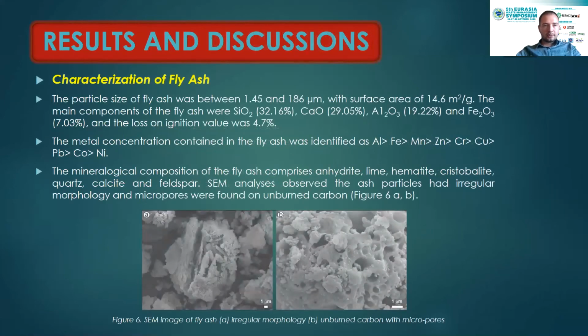Results and discussions. Characterization of fly ash. The particle size of fly ash was between 1.45 and 186 micrometer, with a surface area of 14.6 square meter per gram. The main components of the fly ash were silicon dioxide, calcium oxide, aluminum trioxide, and iron oxide, and the loss on ignition value was 4.7 percent.